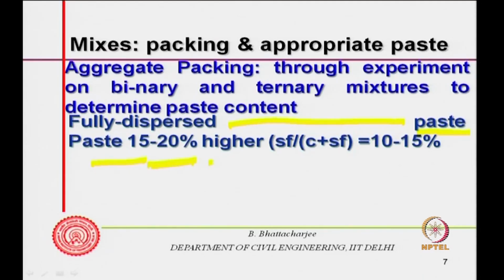So paste 15 to 20% higher, for silica fume, and silica fume generally is 10 to 15%, not 15%, could be 10% is a good amount.